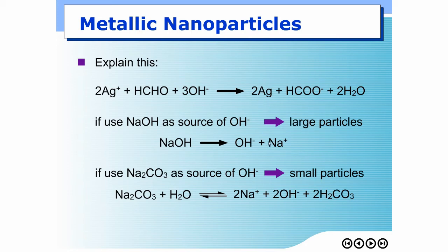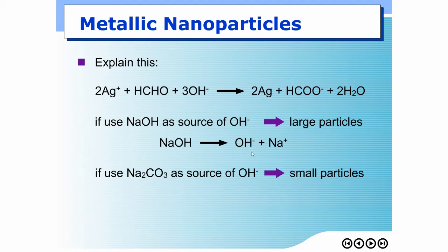But if the concentration of these hydroxyl groups is in excess, that should give you a high concentration of silver 0 even after the nucleation is complete. So that would give you a large value for diffusion for growth species. So growth species would be in the liquid at high concentration, and that does not give you diffusion control